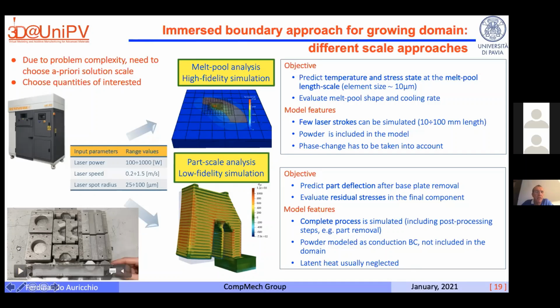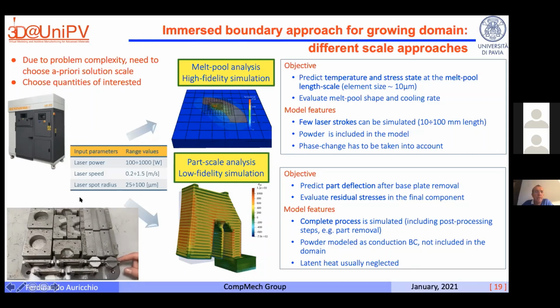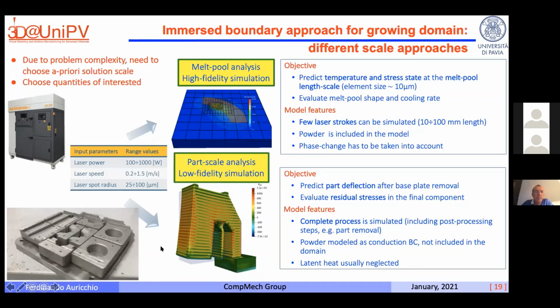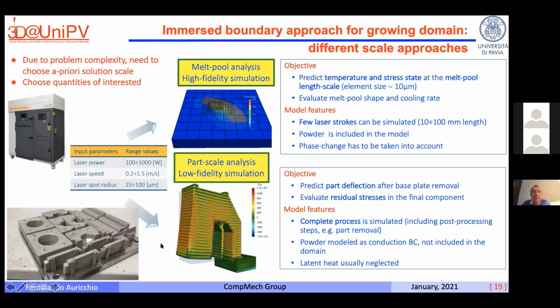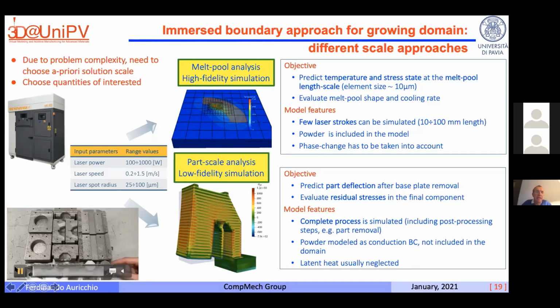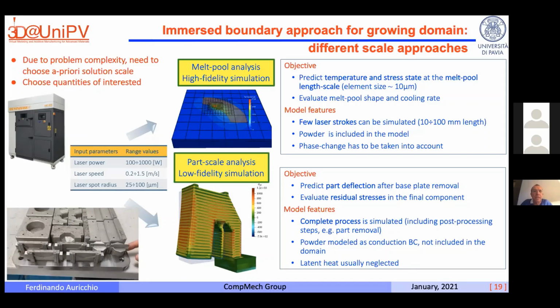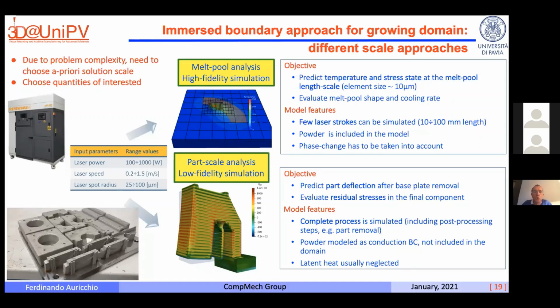And here there is a very nice movie that I want to show you. This is a plate that we 3D printed in our lab, and you can see that the plate is so full of residual stress that it broke the screws that were used to hold the plate to the machine, and now the plate is even bent and can rotate on a table. This is really something you don't want to happen during your production process. So you want to simulate this behavior and try to avoid it. So the question is, how can we simulate melt pool investigations or part scale investigations using this finite cell method?